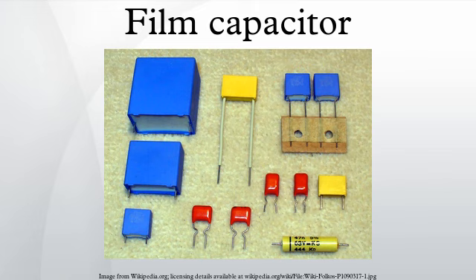This advantage of compactness comes with some disadvantages. The capacitance temperature dependence of polyester film capacitors is relatively high compared to other film capacitors, plus or minus 5% over the entire temperature range. The capacitance frequency dependence of polyester film capacitors compared with the other film capacitors is -3% in the range from 100 Hz to 100 kHz at the upper limit. Also, the temperature and frequency dependence of the dissipation factor are higher for polyester film capacitors compared with the other film capacitor types. Polyester film capacitors are mainly used for general-purpose applications or semi-critical circuits with operating temperatures up to 125 degrees Celsius.